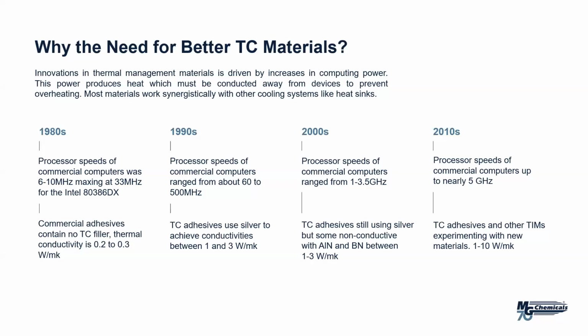So what you had essentially was polymer materials. And I can tell you right off the bat from doing enough measurement that an unfilled polymer material is going to give you 0.2 to 0.3 watts per meter Kelvin. Watts per meter Kelvin is a standardized measurement for thermal conductivity. And the higher that is, the more heat essentially is able to dissipate from one surface to the other.